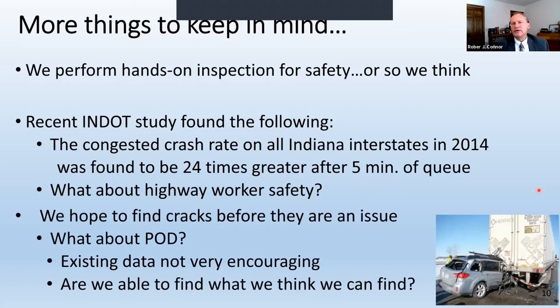So one of the things we did at Purdue with this idea of probability of detection, in the United States, we perform visual inspection. And for these fracture critical bridges, we perform arm's length up close inspection every 24 months. But we have no data, or had no data until we did this study, to look at the probability of detection. In other words, what's the likelihood of finding a crack, a surface breaking crack of a certain size? So we statistically set up a significant number of specimens. We brought in about 30 plus bridge inspectors, real bridge inspectors, not graduate students, put specimens in the air where we introduced fatigue cracks. We knew where they were. We knew their sizes. Unfortunately, the data aren't very encouraging.